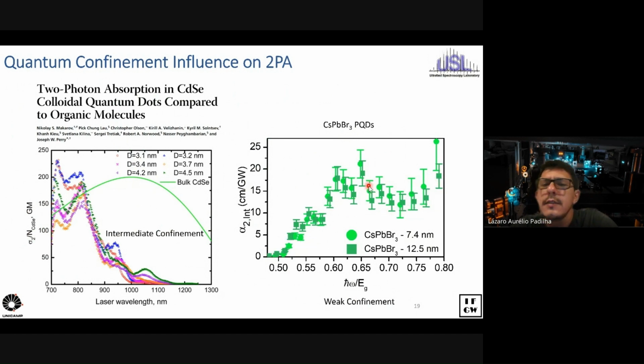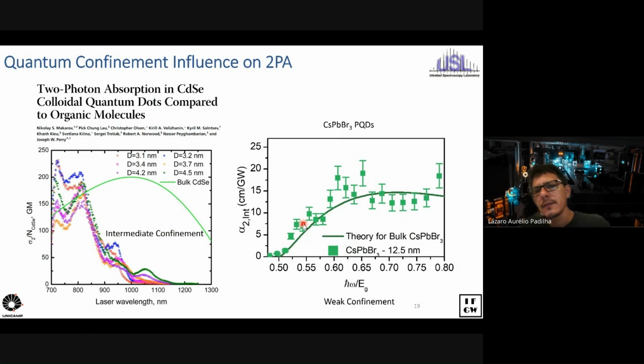This data we're taking exactly at the same time using the same equipment, just replacing samples, so they are pretty similar. And more than that, if you plot the curve expected for the bulk, you see that the data for the quantum dot and what you expect for the bulk are the same. They follow the same trend, which is quite interesting because it shows you that if you're in the weak confinement regime, you are back to your bulk material, as one would expect. And indeed, that's what we see.